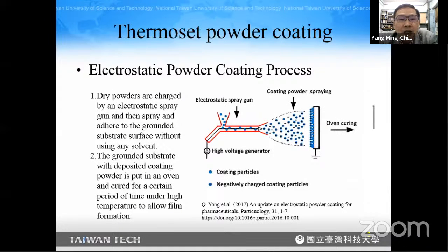Now this slide shows the procedure to perform this thermoset powder coating. It is based on the electrostatic powder coating process. First, dry powders are charged by an electrostatic spray gun and then sprayed and adhere to the grounded surface without using any solvent. So this is more eco-friendly. After coating the grounded substrate, the powder is put in an oven and cured for a certain period of time under high temperature to allow film forming.